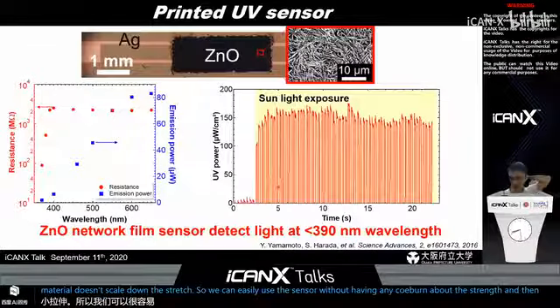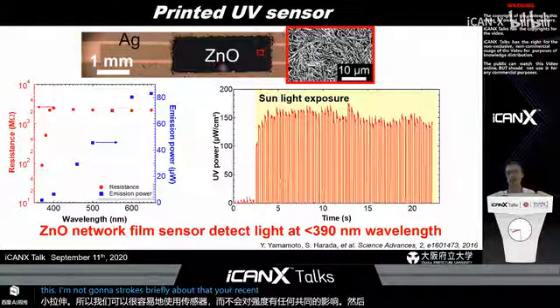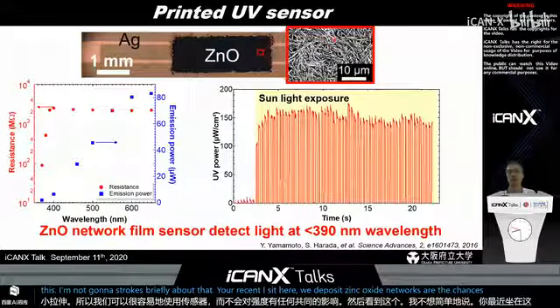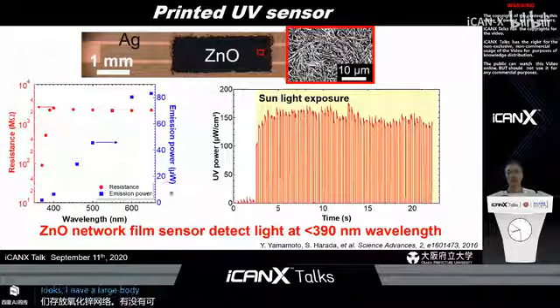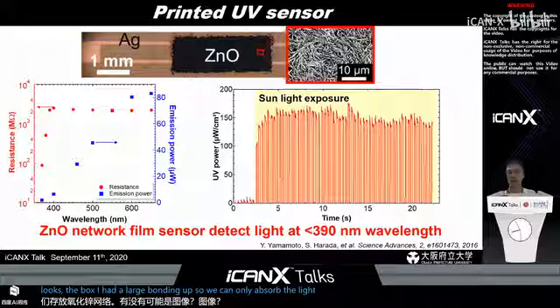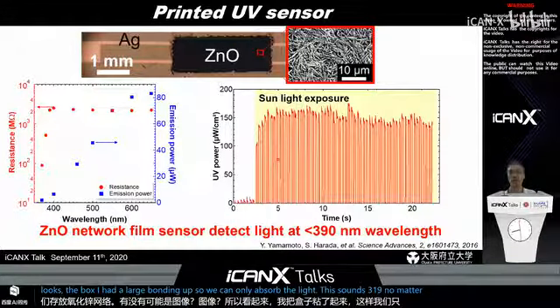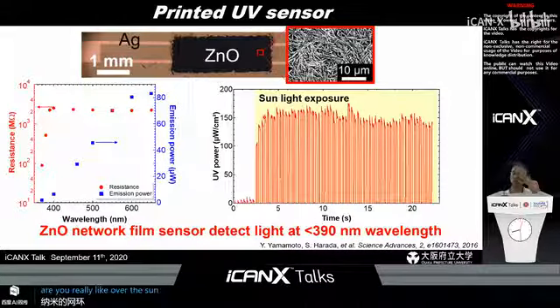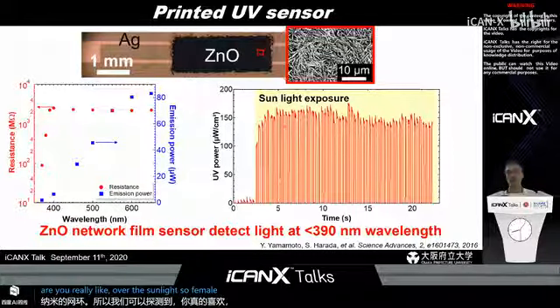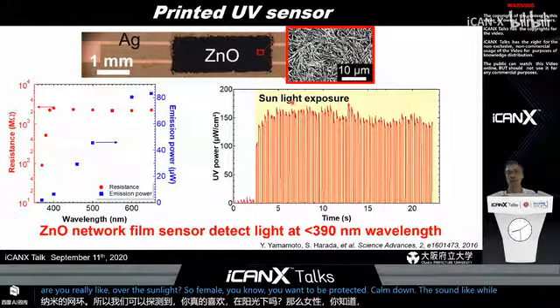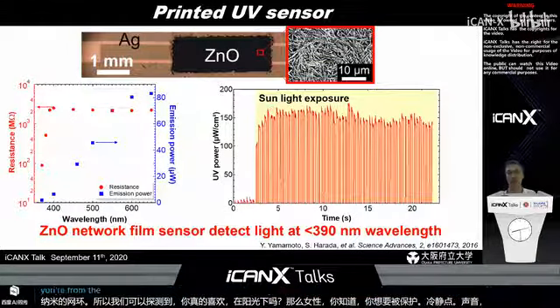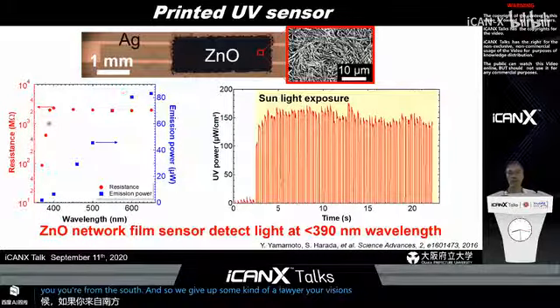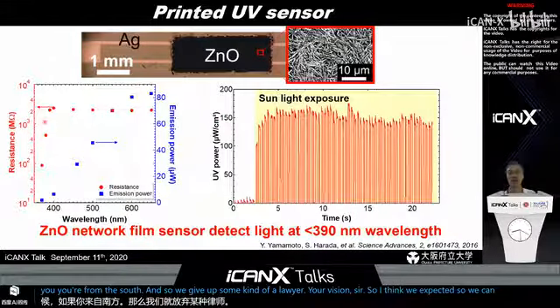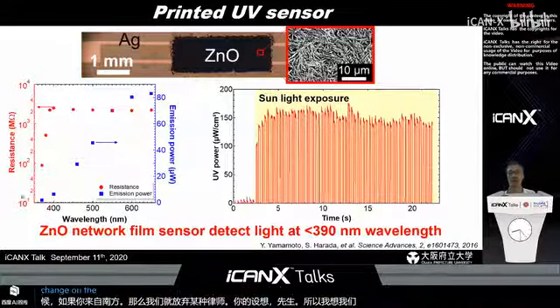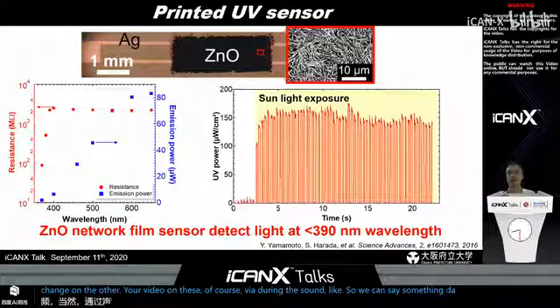I also want to show briefly the UV sensors. Here we deposit a zinc oxide network, as you can see in this SEM image. Since zinc oxide has a large band gap, it can only absorb light at less than 390 nanometer wavelengths, so we can detect the UV light of the sunlight. Some women really want to protect themselves from the UV from the sunlight. So we developed a UV sensor, and as we expected, we can see a huge resistance change in the UV region only.